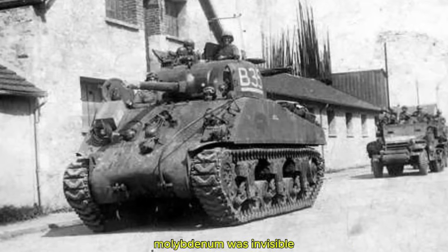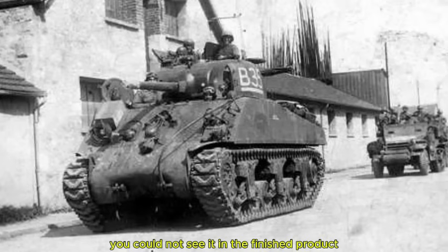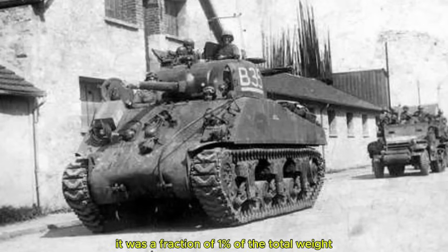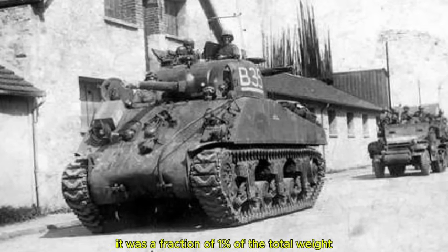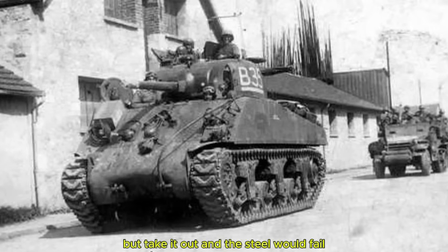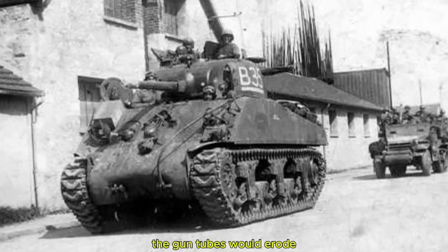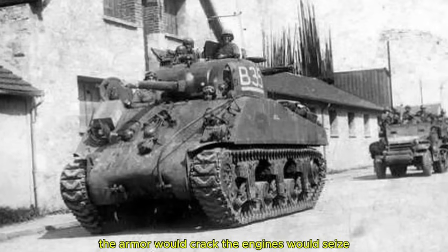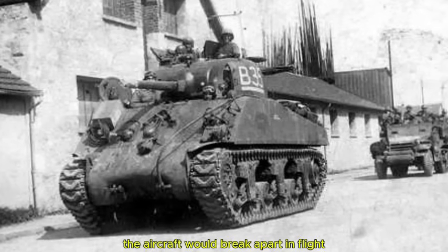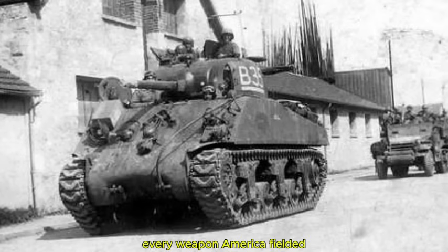Molybdenum was invisible. You could not see it in the finished product. It was a fraction of a percent of the total weight. But take it out, and the steel would fail. The gun tubes would erode, the armor would crack, the engines would seize, the aircraft would break apart in flight. Every weapon America fielded depended on a material that, for practical purposes, came from one mountain in Colorado.